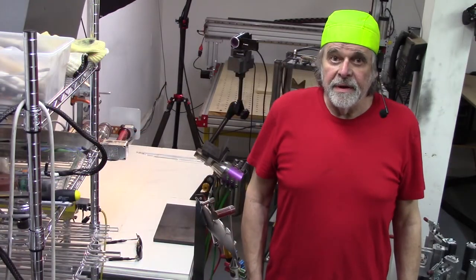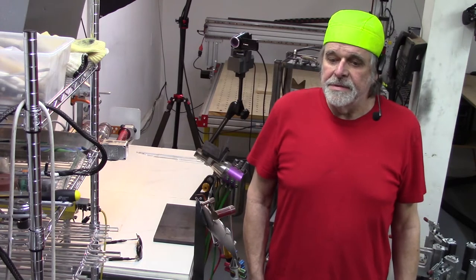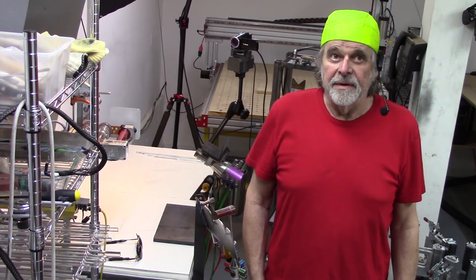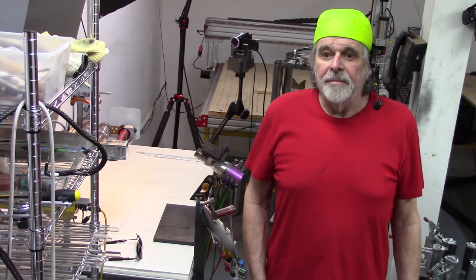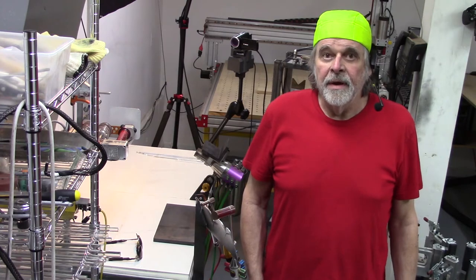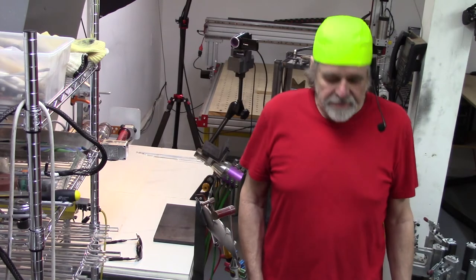Well, the pieces are cut and put together with the stainless steel safety wire, and they're coming out of the kiln now, so it's time to assemble. I've pre-made all of my punties and moils because it's pretty boring and you don't need to see that again. I'm gonna get the piece out of the kiln and start squeezing it together. I'm using the fixed size 1-inch dies in a hexagon pattern, and as the pattern gets squeezed, I'm probably going to switch to the 7/8. Then when the pattern is fully consolidated, I'm gonna pull it down just a little bit.